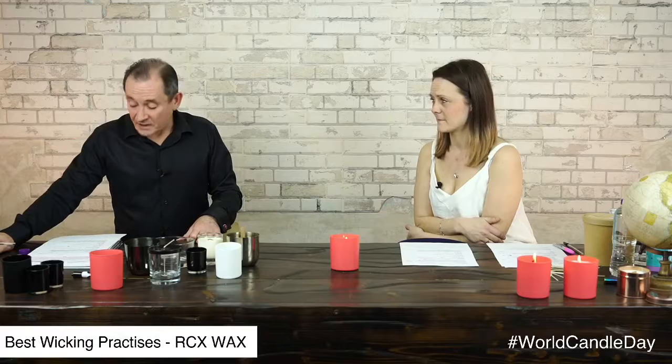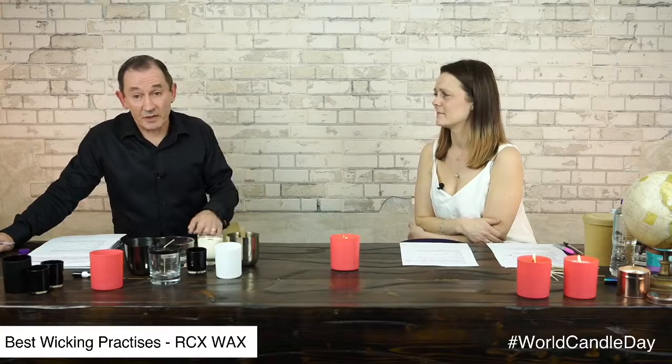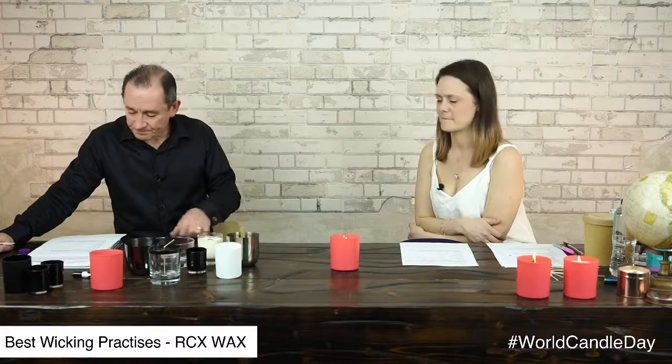But I think what I can say, maybe not a best fragrance load, but we can give you a typical maximum. Typical would be between 8% and 10%. Maximum probably 12. Some people go for 12. Some go down as low as 6, maybe even lower still, I'm not sure. The lowest that we've done, I think, has been 6%.